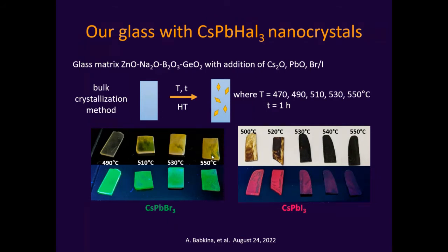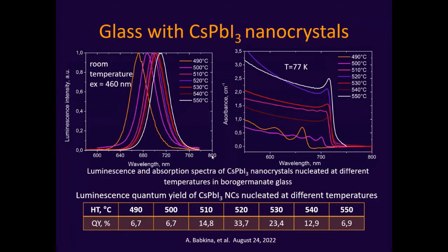The most lovely thing about nanocrystals inside of the glass matrix is that we can vary their size by varying the regime of heat treatment. And the second lovely thing is that all these crystals are of the nanoscale, not of the macro scale. So we are working inside of the region of the size effects. What does it mean? It means that while raising the temperature or the duration of the heat treatment, the mean size of the crystal increases with it, and the wavelength of the luminescence maximum and the exciton absorption maximum are shifting towards long wavelengths.